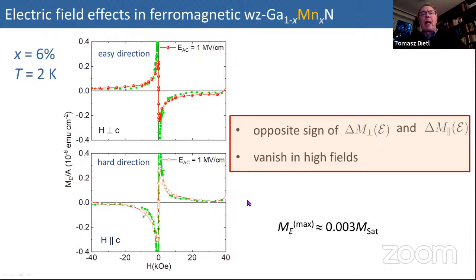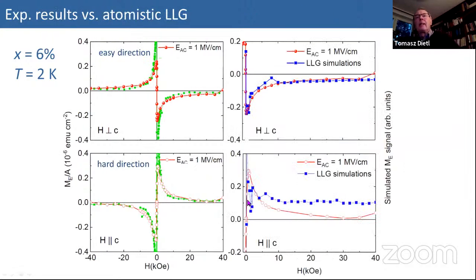Okay, so how can we describe this theoretically? Here you have these Landau-Lifshitz-Gilbert (LLG) simulations. I remind you that we do not use any macrospin approximation here. And you see that without adjustable parameters, you can explain the sign reversal and more or less the magnitude of the effect. Of course, simulations are not always without some noise, but basically we can understand this effect from this simulation, this kind of shape and this kind of sign of the effect.